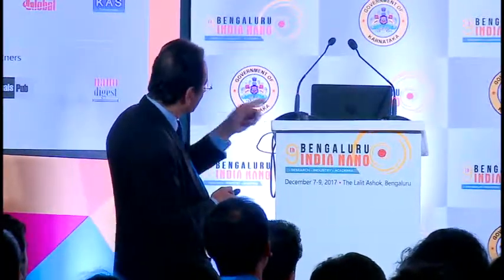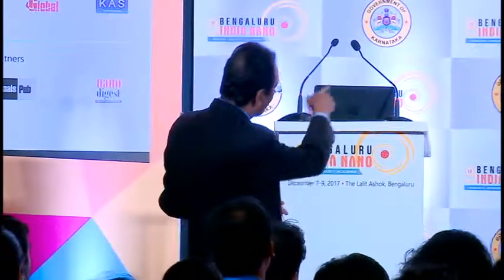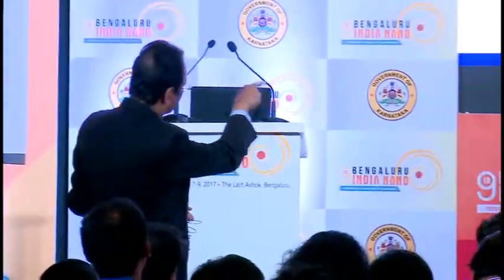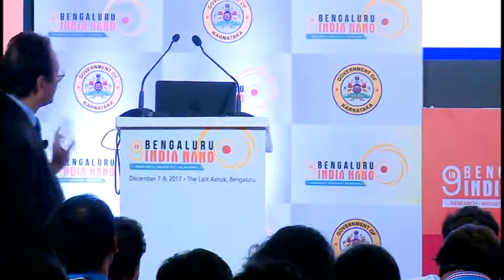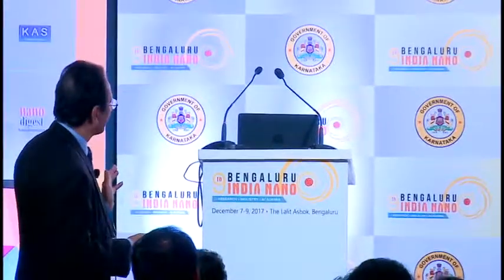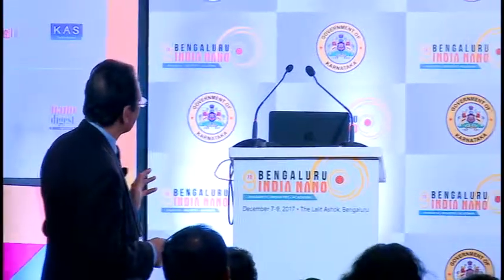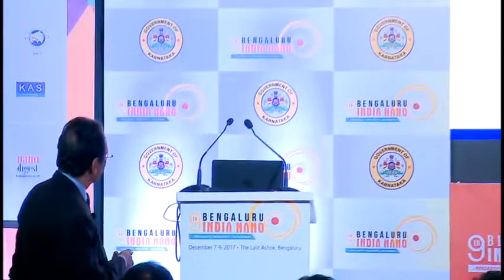So you see, the red line in the middle is the X-ray that comes out, and the peaks on it are actually characteristic X-ray peaks of the elements. And he developed an algorithm which can essentially measure the composition. For example, I'll give you a comparison.